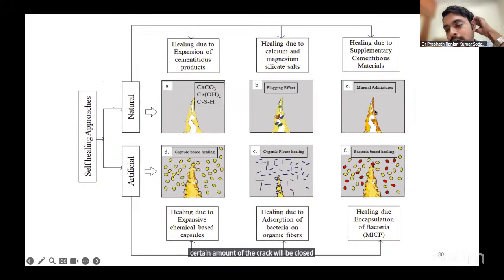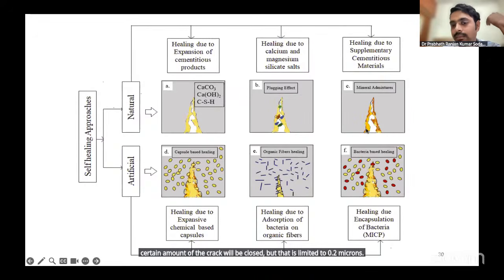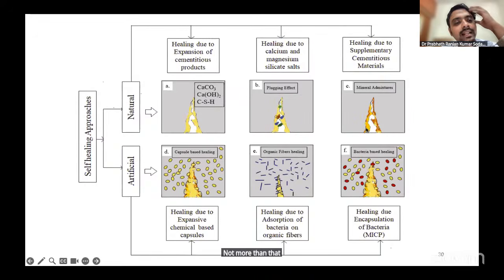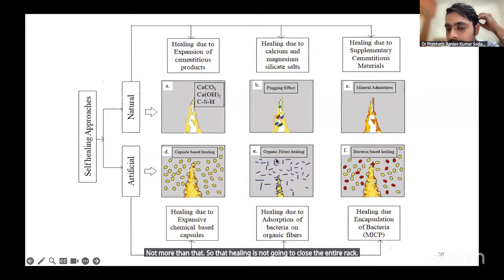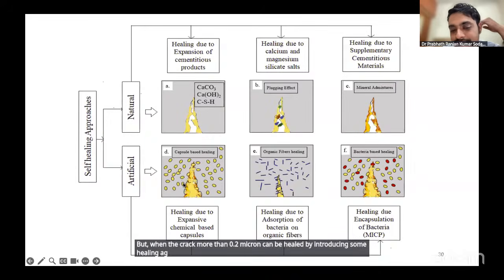But that is limited to 0.2 microns, not more than that. So that healing is not going to close the entire crack. But a crack of more than 0.2 micron can be healed by introducing some healing agents artificially, which can be chemical based, or organic fiber based, or by encapsulating bacteria.